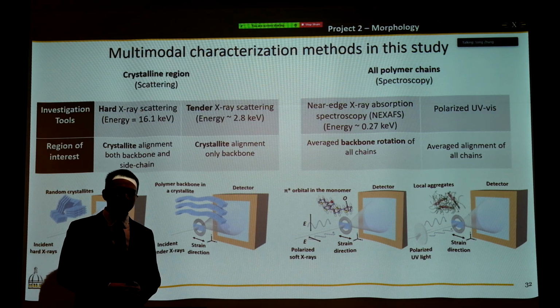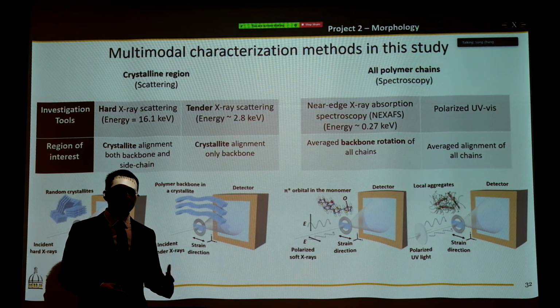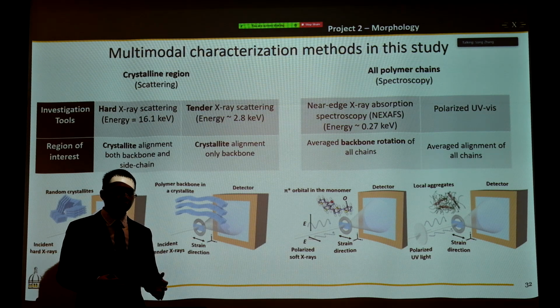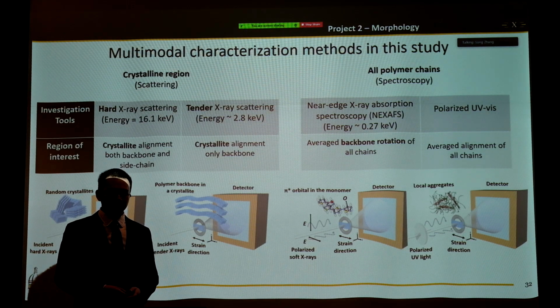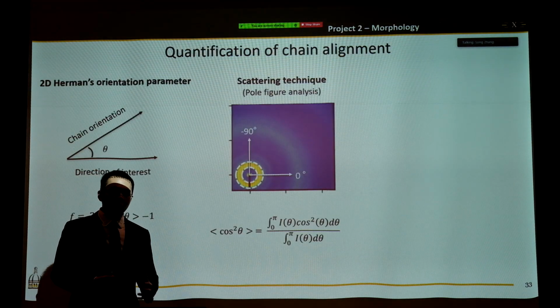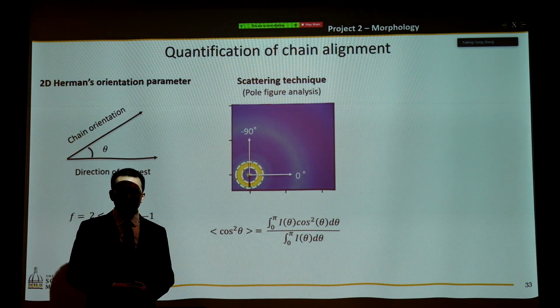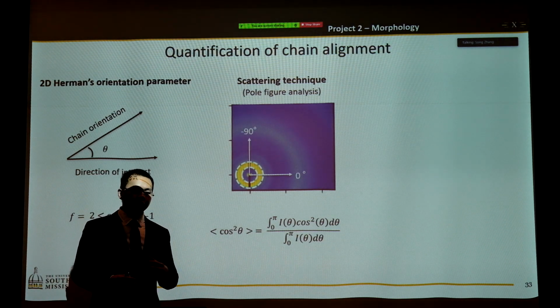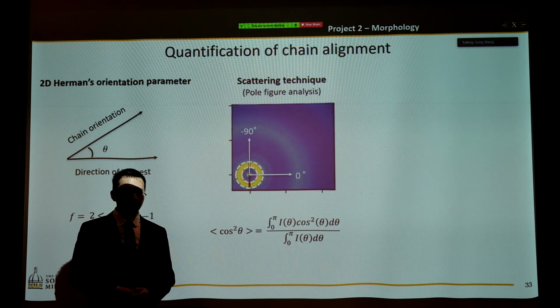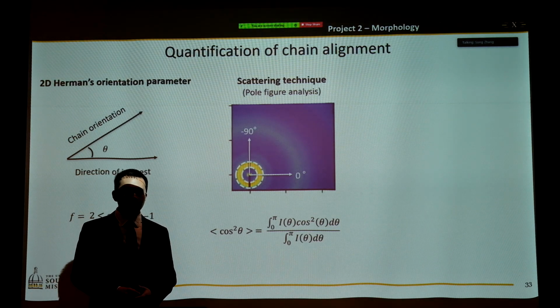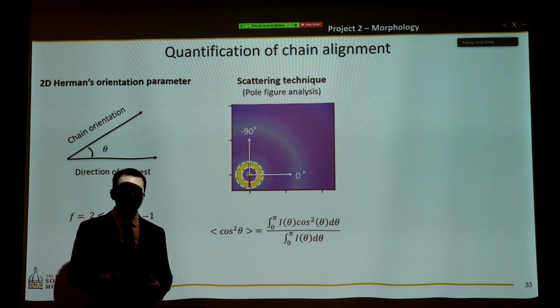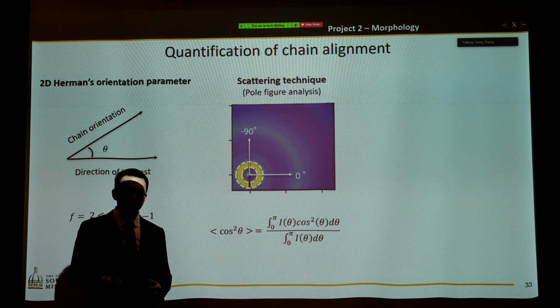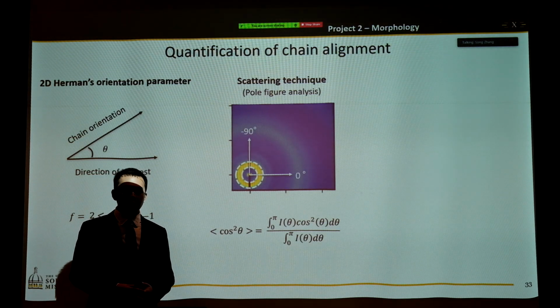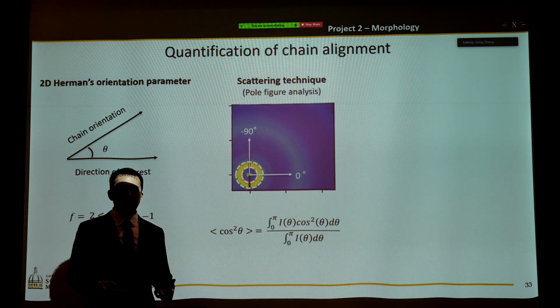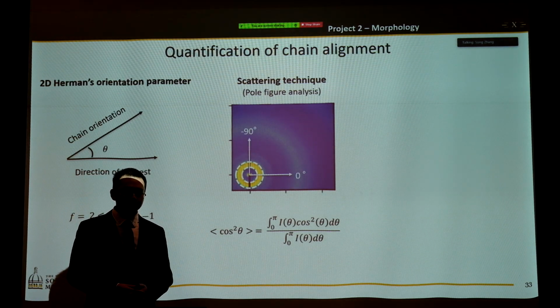By using polarized UV-Vis, just like the P3HT study, we can look at the average alignment of all polymer chains. And in order to quantify the degree of alignment, we will be able to use this 2D Herman's orientation parameter, or F value. If F is equal to 1, it means the chain orientation and the direction of interest are parallel to each other. If F value is equal to 0, it means it's basically isotropic scattering.